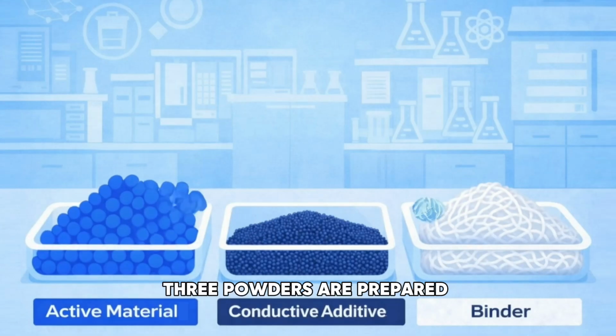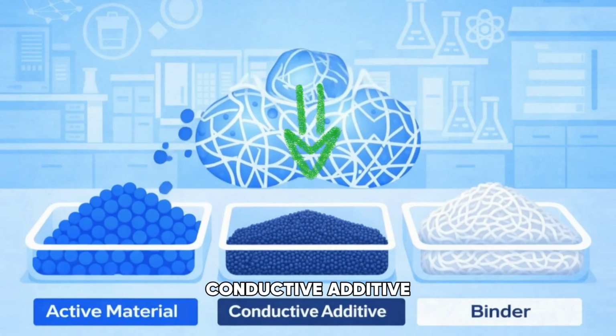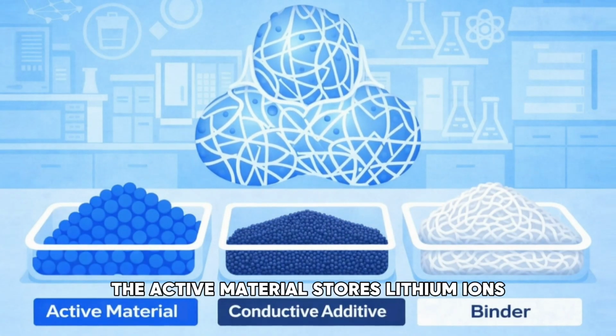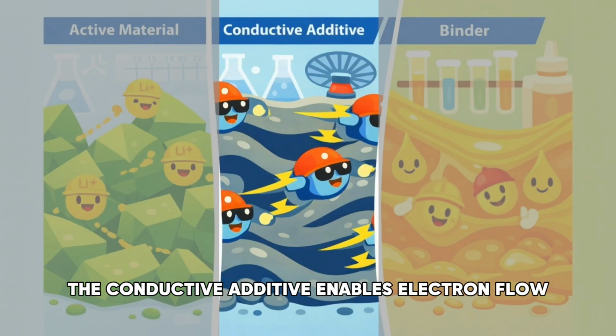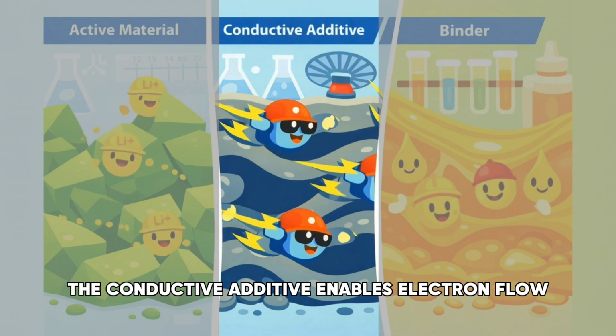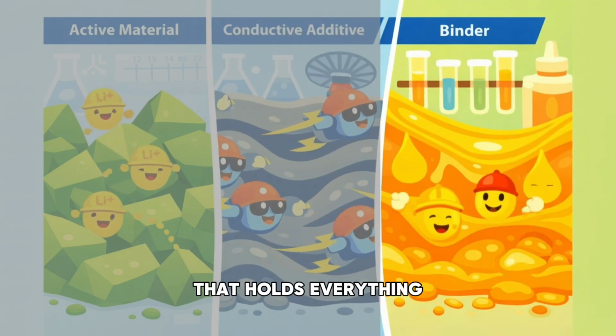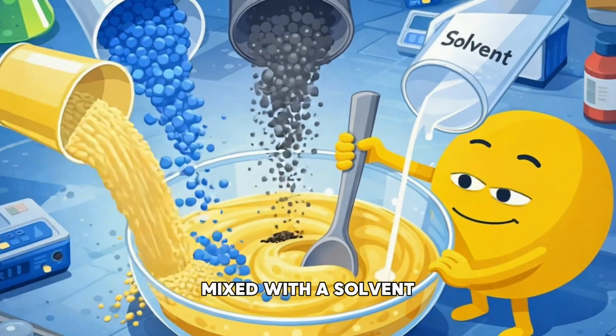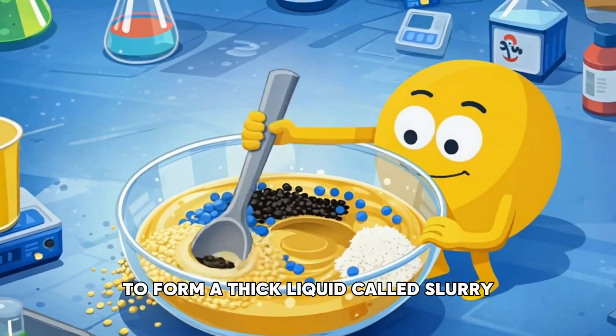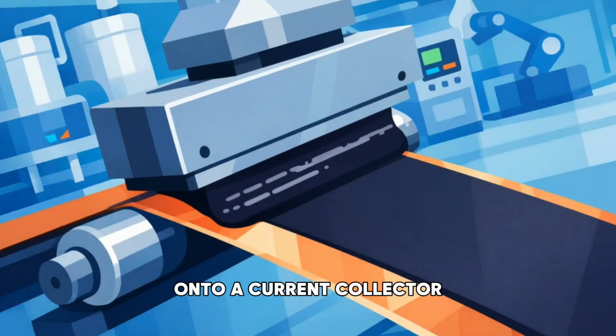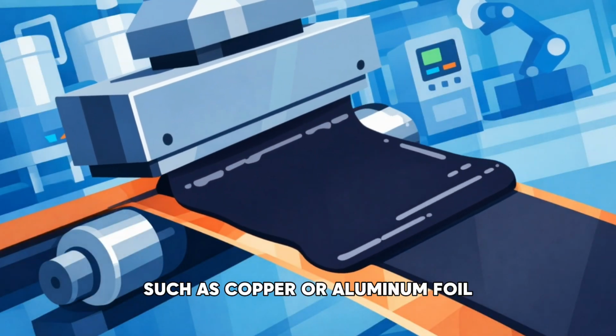First, 3 powders are prepared: active material, conductive additive, and binder. The active material stores lithium ions. The conductive additive enables electron flow. The binder acts as the adhesive that holds everything together. These powders are mixed with a solvent to form a thick liquid called slurry, which is then thinly coated onto a current collector, such as copper or aluminum foil.